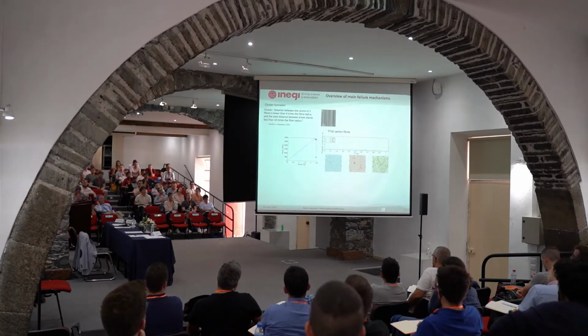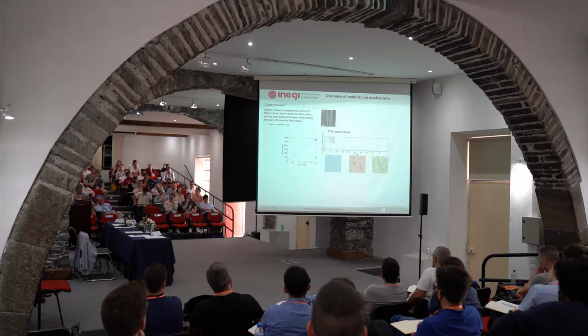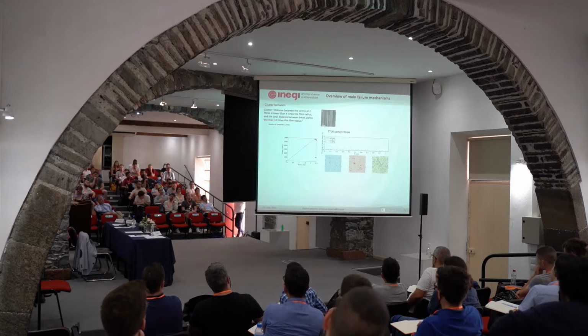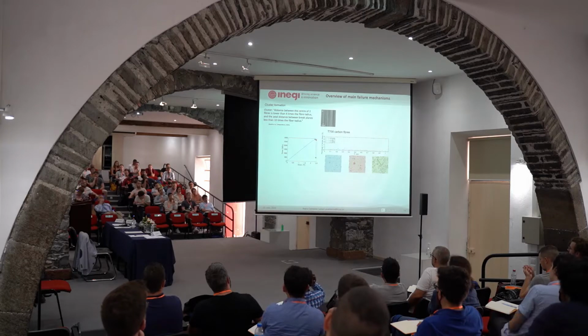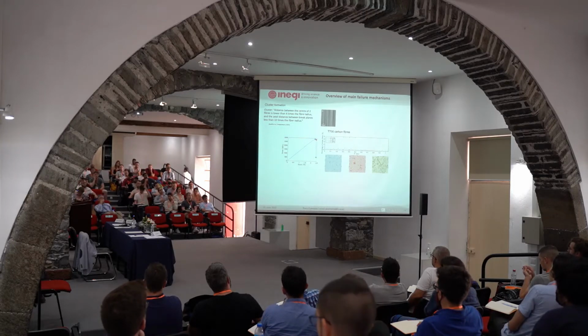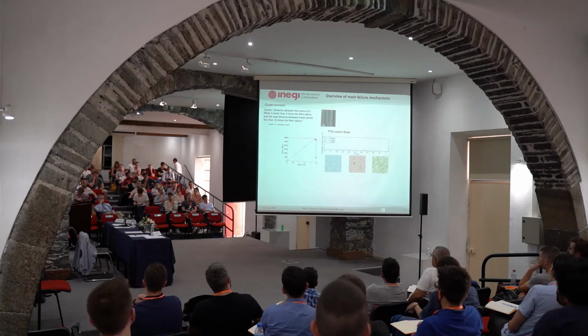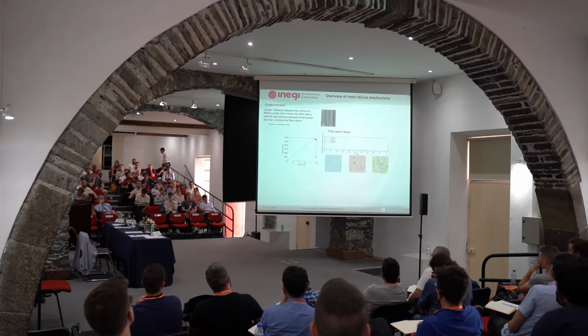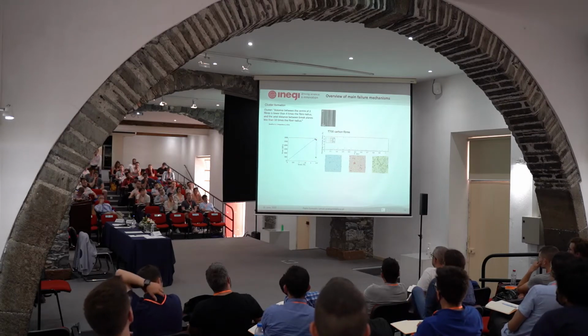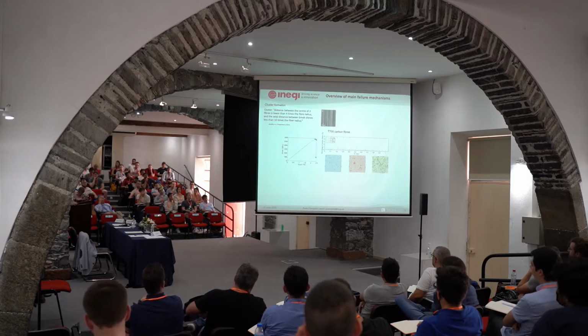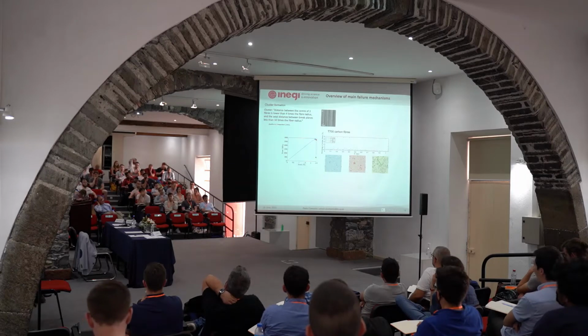Now what we already knew from some tests that were done also by Southampton University in the synchrotron is that the failure, longitudinal tensile failure, is controlled by a process of formation of a cluster of broken fibers. And a cluster can be whatever you want. So we are using the definition proposed by Jens Wolf from KU Leuven that considers that two fibers are in the same cluster if the distance between the centers of the two fibers is lower than 4 times the fiber radius, and the axial distance between the break lengths is less than 10 times the fiber radius.